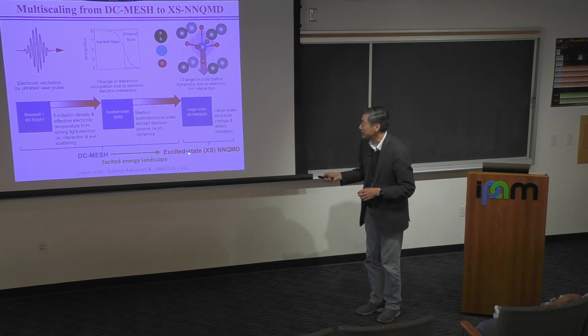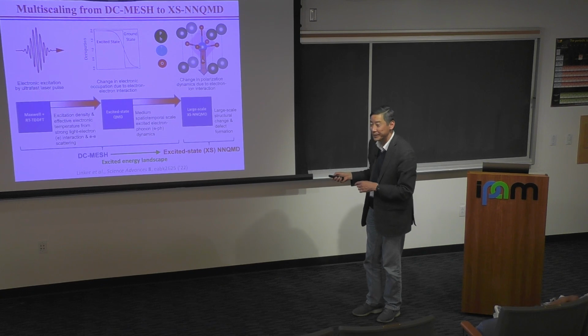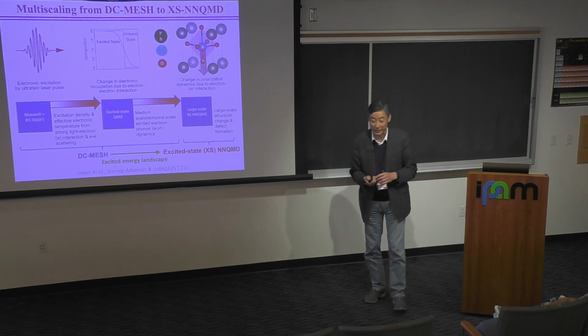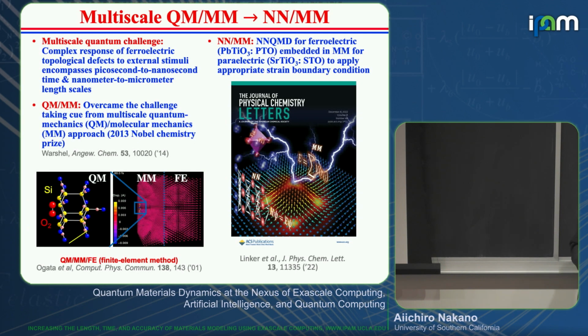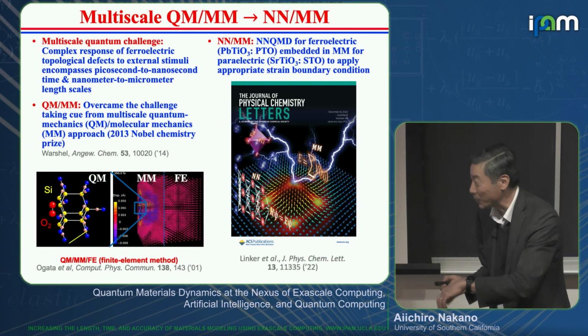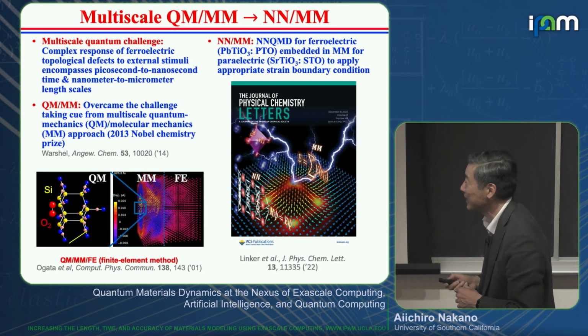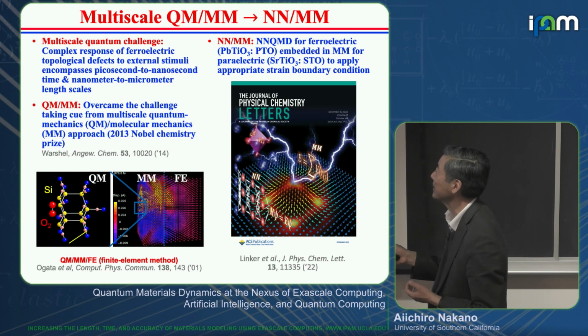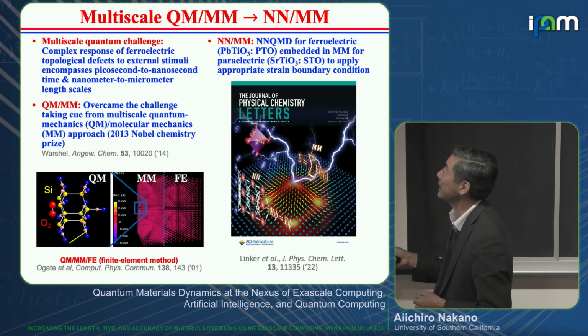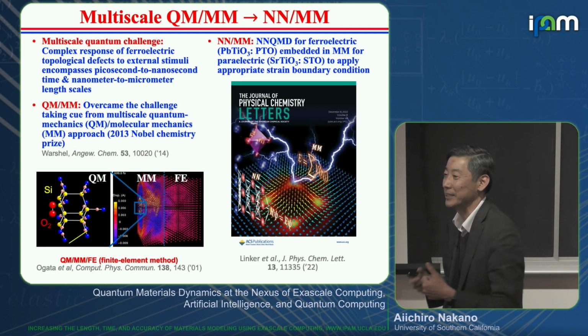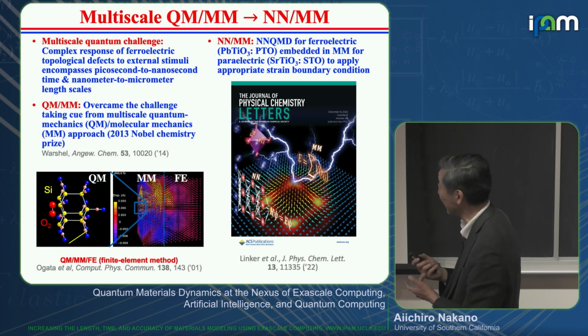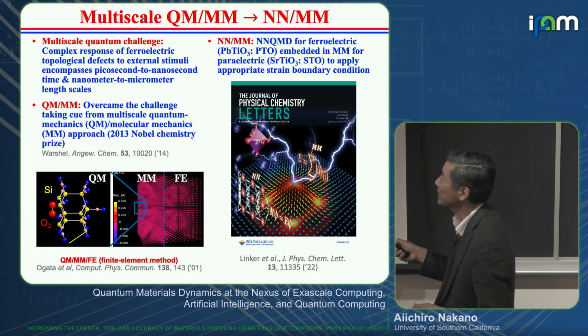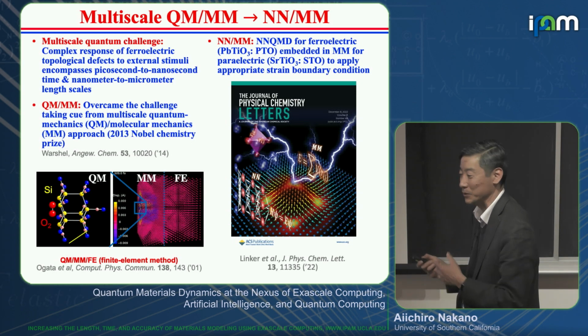Okay, so we also have a multiscaling method in which excited state neural network quantum molecular dynamics learns the excited energy landscape produced by this first principles DC mesh, so that we can do much bigger systems. More recently, we have also developed a multiscale NNQMD method. Here, in the multiscale quantum challenges, we are studying ferroelectric topological materials. The complex response of this ferroelectric topological defect to external stimuli like light, electric field or mechanical stimuli encompasses the picosecond to nanosecond time scale and nanometer to micrometer length scale. So we cannot do first principles.